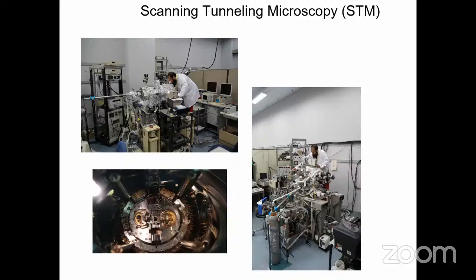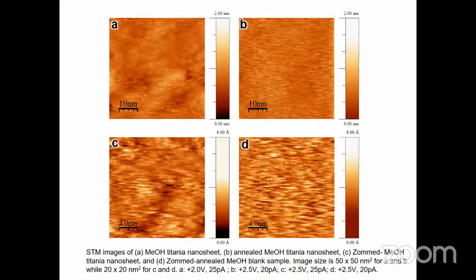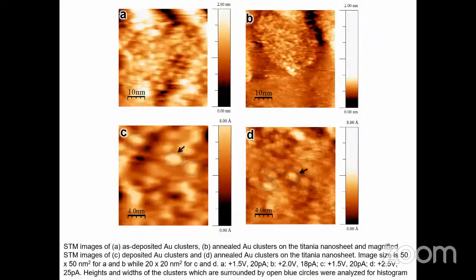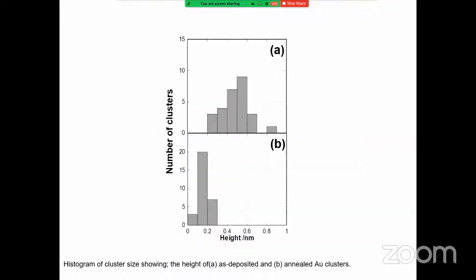We have the titanium nano sheet, and we measure it as a reference sample before and after annealing to see what kind of changes happen to the substrate before we deposit our Gold 9. Once we deposit our Gold 9, we saw the Gold 9 before and after annealing. And this is a close imaging of a single nanocluster deposited on nano sheet using the STM itself. We create a histogram from it, and we saw the size has been reduced, and this is related to removing the ligands from the nanocluster.